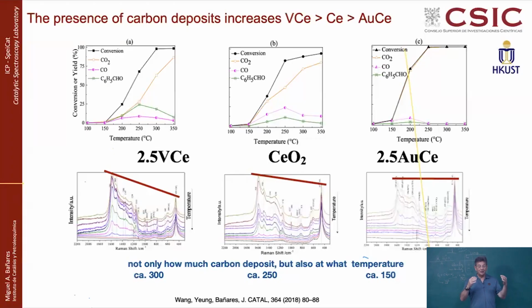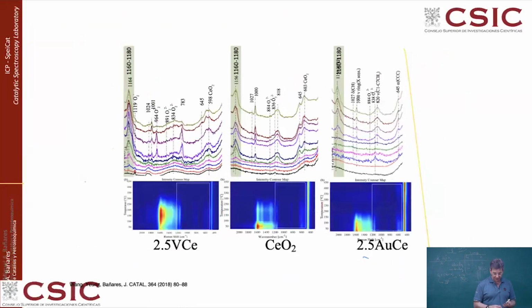It is not only that the total amount of carbon deposits qualitatively is bigger or smaller, it is that if the surface gets clean at dramatically lower temperatures, this is telling you, wow, there is a major difference on the performance, and there is clearly a major difference about the nature of carbon deposits which are built up on the surface, which somehow correlate with what is happening in the reaction. So we can focus at different areas of the Raman spectra to find out what is happening. What we are observing is just a projection of the intensity of the hydrocarbons that we were running out of at 300, 250, 150, but now we look at this box with lower frequency.